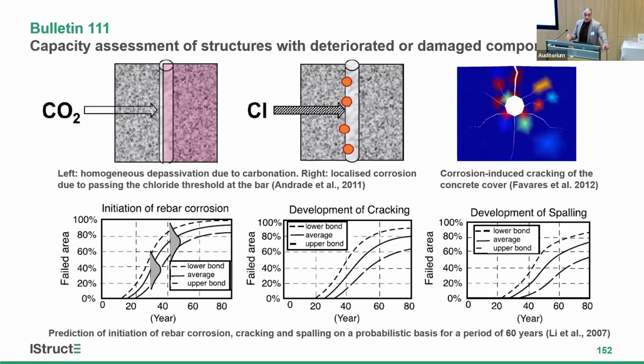It's mainly because on a day like today, it's freezing cold and we get frost on the road, so we put salt. That salt melts and penetrates through the concrete cover, and concrete is essentially like a sponge. It has porosity, and the salt is sucked into the concrete. When you get to a certain level, called the chloride threshold level, which is normally 0.4% of the cement, it changes the passivity at the interface between the concrete and the steel, and that reacts and starts the electrochemical process of the corrosion. And what happens is, you have an initiation period.